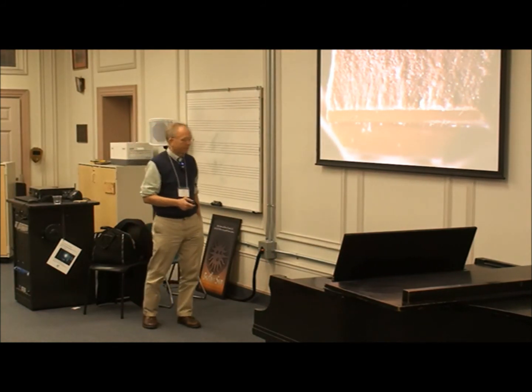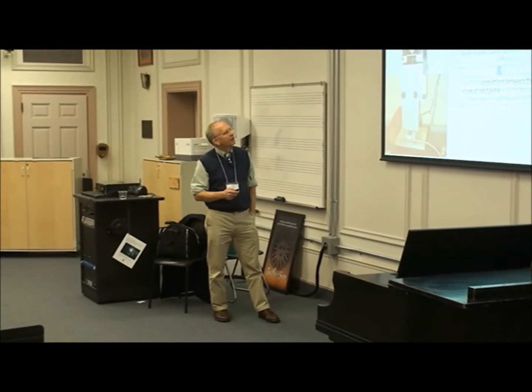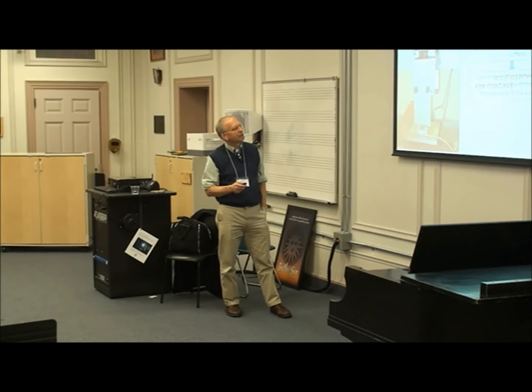All right, so here's a material, and we're looking at fractography. So we're breaking this. And this is a composite material. Worldwide sales, I think, are $6 billion a year in this material. So we broke it in three-point bending, and we measured the force during fracture, and we did it at different temperatures. We did it over a range of temperatures. It turns out it's a very high homologous temperature, so it melts just below body temperature, this particular material. And so we're looking for correlations between the relative areas that we measure on the fracture surface and the temperature work of fractures. So here's the load, and there's the displacement during fracture, and there's all the different temperatures.